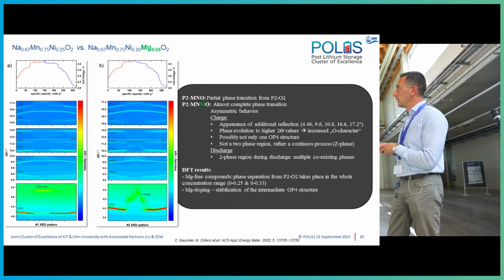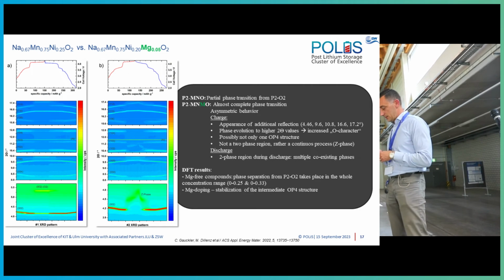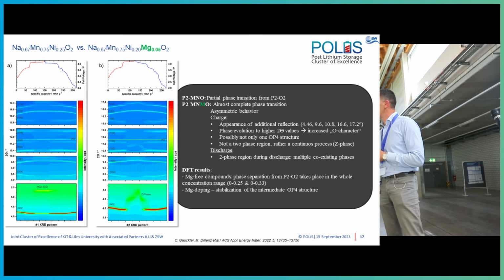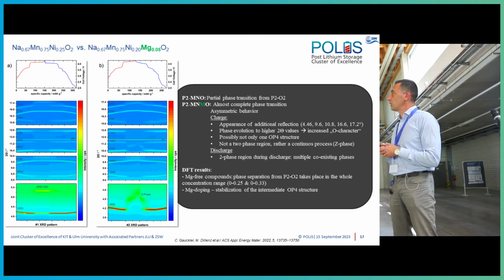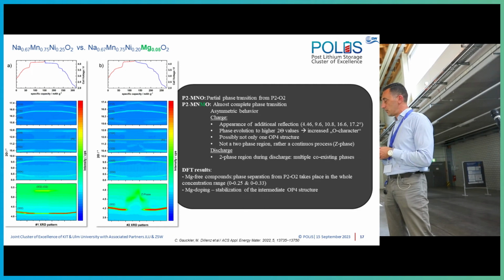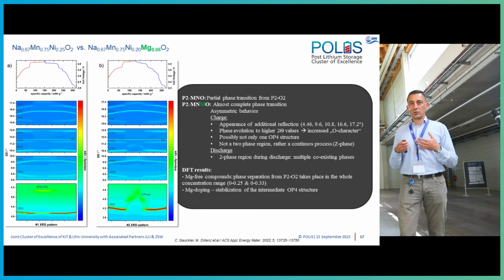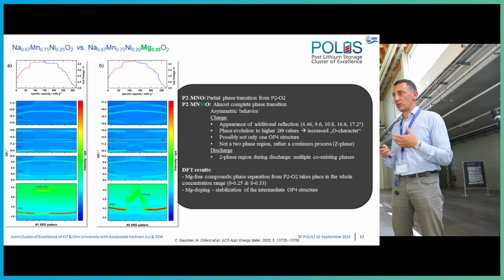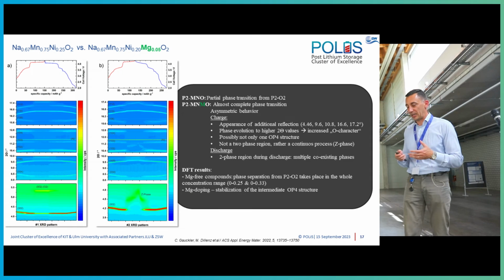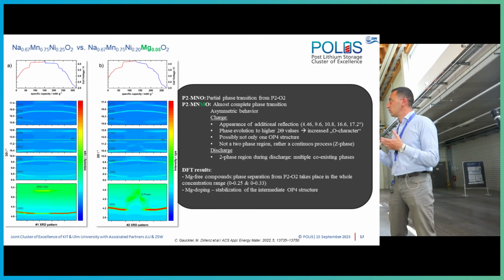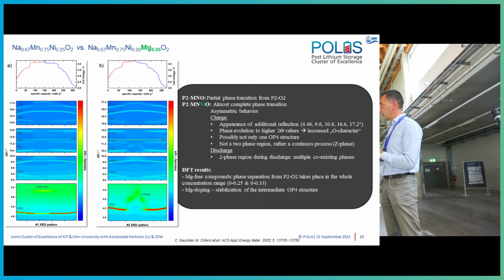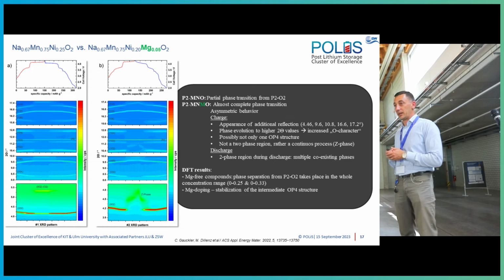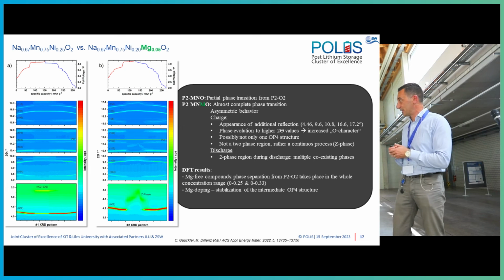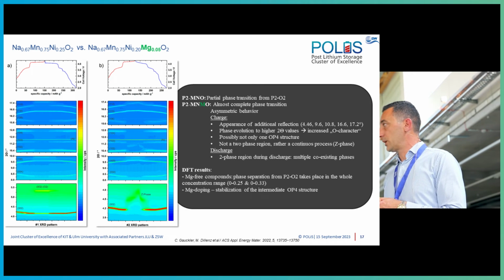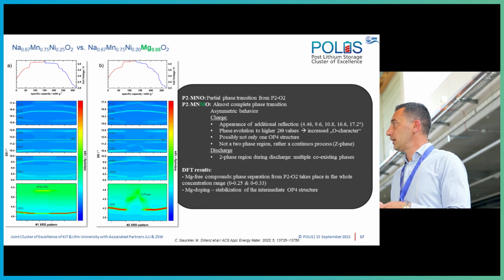But then if we actually compare the doped material with the undoped material, we see a completely different behavior. So for the magnesium doped, we have an almost complete phase transition. There is not only one OP4 phase, as it was pretty much announced in literature, yeah, but we have an evolution of phases. And then, thanks to the work of Manuel, Olga, Mosin, and Axel, it was clear that the magnesium doping can actually stabilize the intermediate OP4 structure.